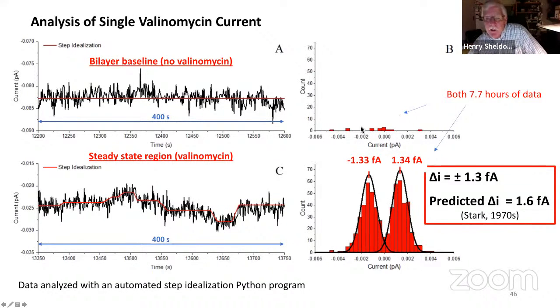And what you see up here in the bilayer baseline, there's essentially no steps that are being measured or detected by the Python script. And down here, you get this bimodal distribution that's centered at 0 current. And it's symmetrical, and it's got a peak at plus 1.34 femtoamps and a peak at minus 1.33 femtoamps.